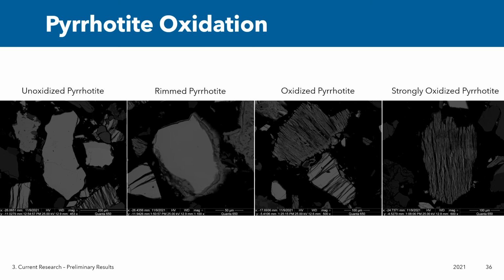The pyrrhotite grains in the initial 2020 sample show varying degrees of oxidation, which is evident from these backscatter electron images. Here I'm showing examples of unoxidized pyrrhotite, pyrrhotite that has been rimmed with iron oxide, and then moving to pyrrhotite grains that have been substantially oxidized until almost all of the pyrrhotite has been replaced with iron oxide.